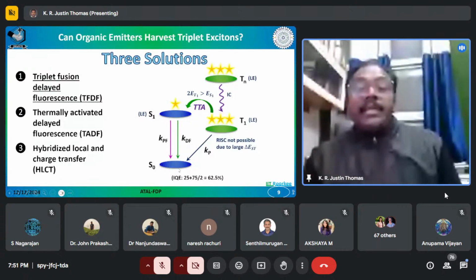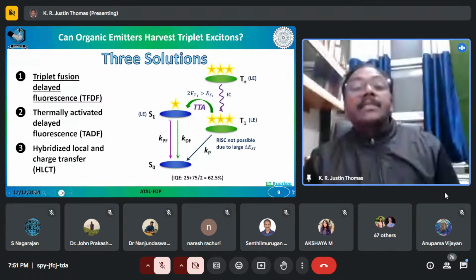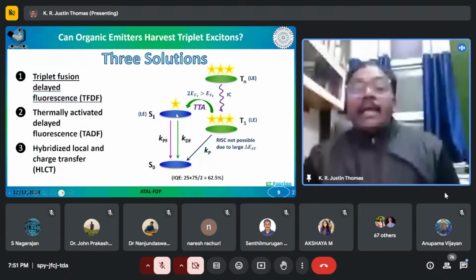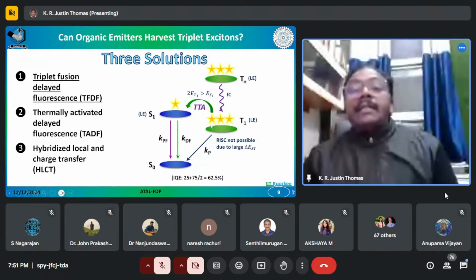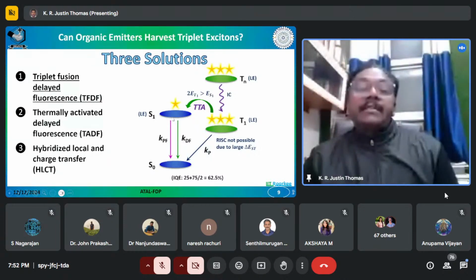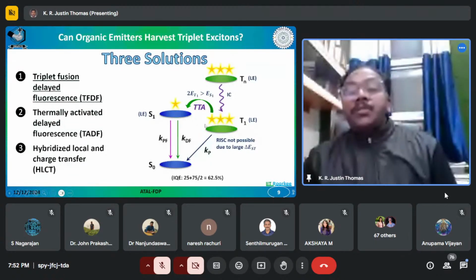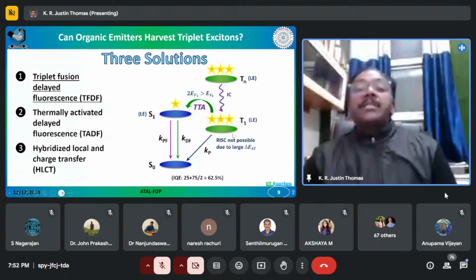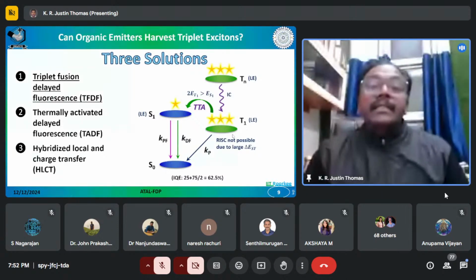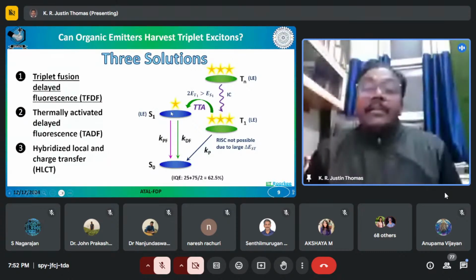So you have a molecule in the ground state and then you shine light and it gets excited, goes to the singlet excited state. And in this kind of molecule, the ground and the first singlet excited states are locally excited states. That means they involve a pi to pi star transition. And at the same time, there is an important aspect about these kinds of molecules, where the triplet energy of this molecule is nearly half of their singlet energy. So that means that two triplet excitons in principle can have an energy higher than the singlet. So that is the criterion required for this.